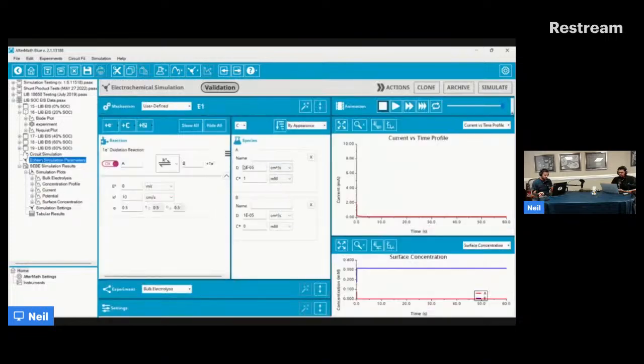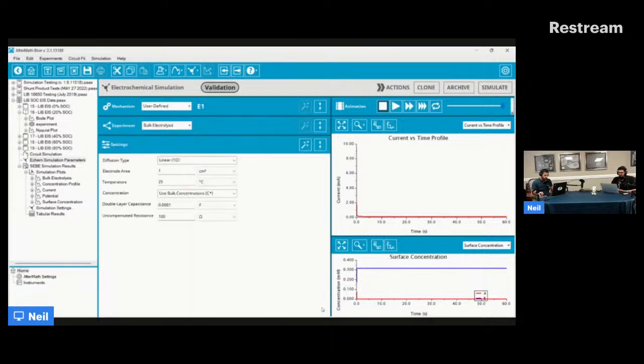Now, instead of changing the diffusion coefficient, what I've done is gone in here. As part of our software, you can adjust the double layer capacitance and the resistance. This is the time constant, basically. So I just added some uncompensated resistance, let's just say 500, since this is a hydrogel, so it's more resistive. And I added a little capacitance. I just picked some small number, maybe 100 microfarads. Let me simulate this. Okay, so I've added capacitance because before these were zero. It was not taking into account double layer capacitance or anything. Now let's zoom in and see.